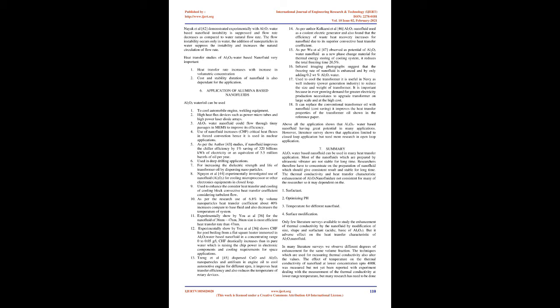Patel et al [36] conducted an experiment for Al2O3 water nanofluids and measured the critical heat flux, CHF. They further investigated that the critical heat flux of nanofluid increased three-fold compared to pure water. This is an unprecedented phenomenon. Although in his experiment, the average size of bubbles increased and bubble frequency decreased significantly as compared to pure water.